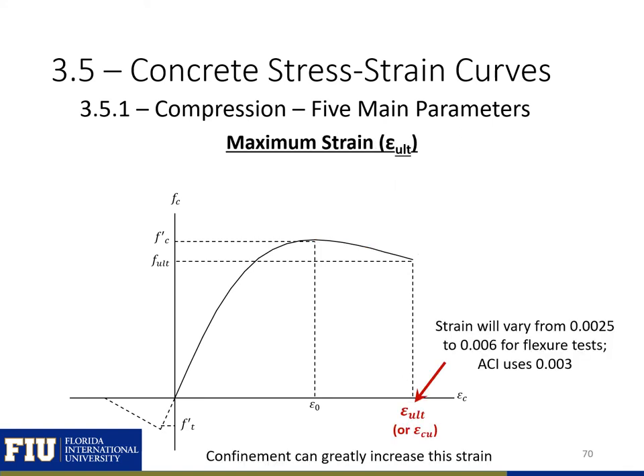The next parameter is the maximum strain that the concrete can hold before failure, or ultimate strain. This variable is either epsilon ultimate or epsilon cu. The maximum strain can vary between 0.0025 and 0.006 for flexure tests, without any confinement effects. ACI assumes this strain to be 0.003. Note that the maximum strain can be significantly higher than this when confinement effects are taken into account.